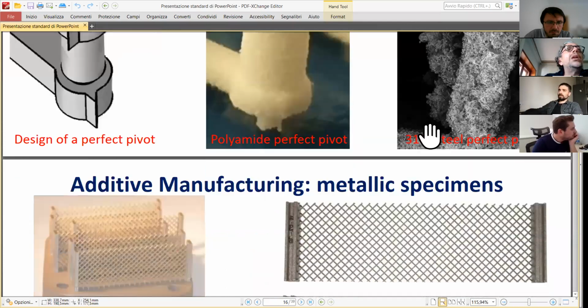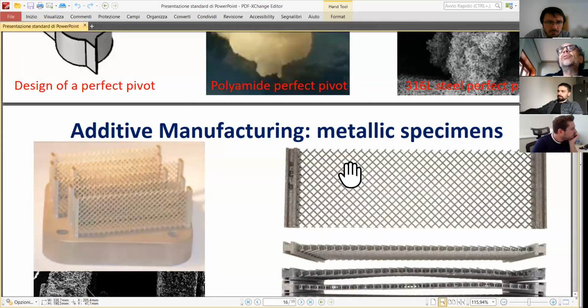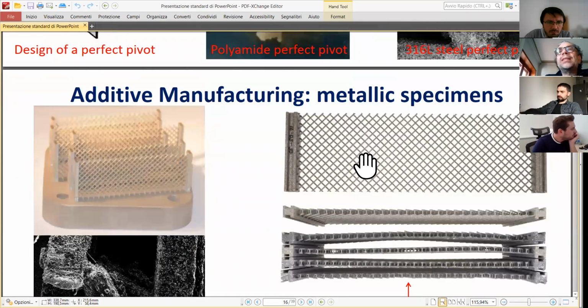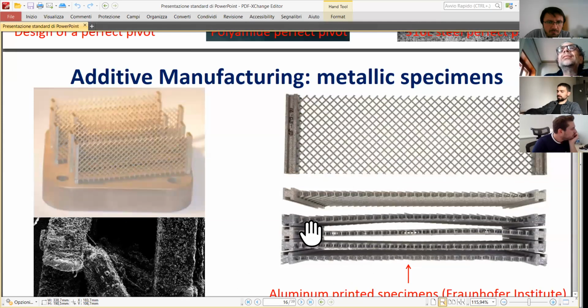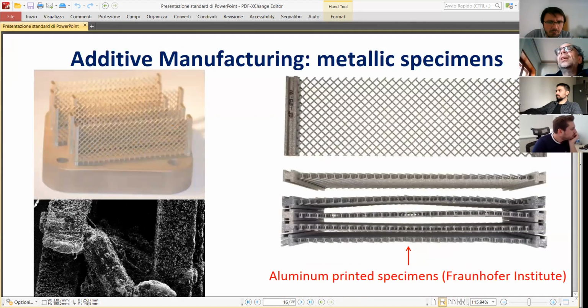Okay. So in the additive manufacturing of metallic specimens, we are having serious troubles. You see, this is a specimen after printing. They need to be thermally cured for becoming straight, and it can be very difficult. But at the end, at the Fraunhofer Institute, they did manage to get straight specimens.